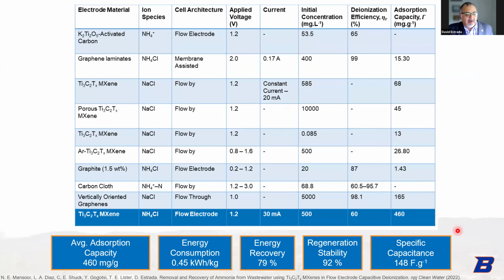Right. So we did do some benchmarking, say, well, why not just use graphene? Graphene has been used in FE-CDI. Their adsorption capacity is much lower when looking at the same salt. And graphene, if you've ever worked with it, it's hard to functionalize and keep stable in water, maintaining its conductivity. And especially in salt water, we actually use salt water to crash graphene flakes out and collect them to create graphene papers for our ink synthesis.